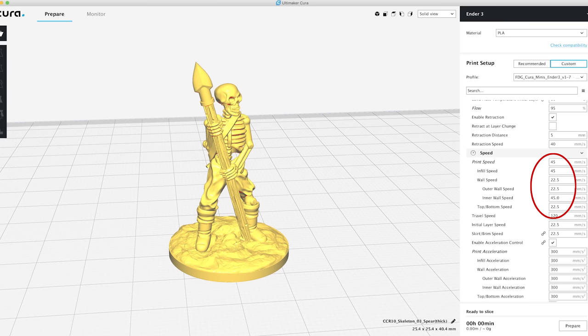Now, for me, what I've found with a 0.4 millimeter nozzle printing at 0.1 or even as low as 0.08 layer height, this 22.5 millimeter per second outer wall speed works fine. You get nice sharp details, but the nozzle is moving fast enough that it's not heating those lower layers as rapidly as if you printed at a slower pace. It actually is going to be a little slower than this, but I'm going to get to that in a moment when I get to jerk. But for right now, 22.5 for the Ender 3 works fantastic.